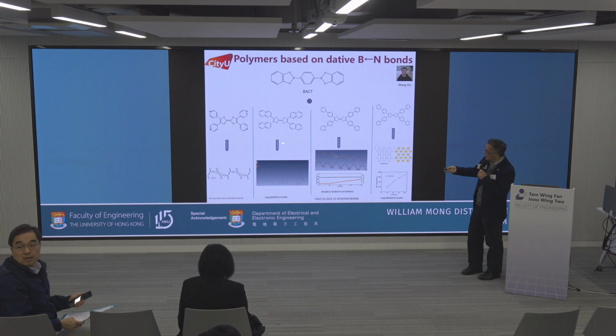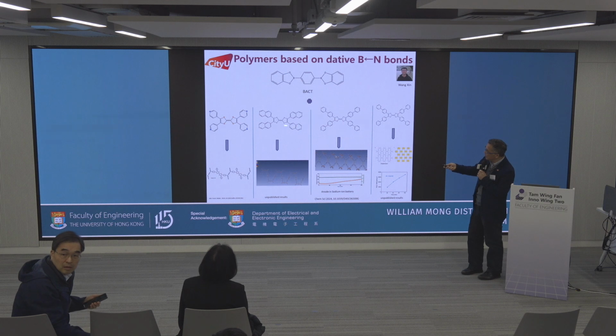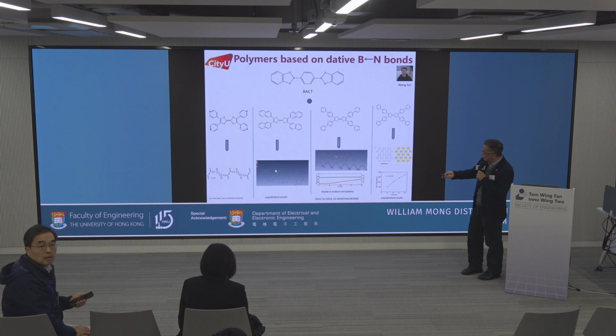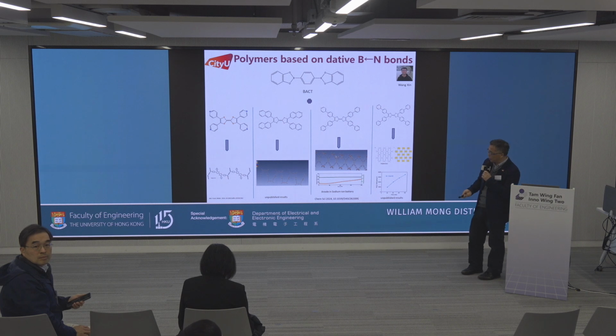isoquinoline, you can see that here it is still isoquinoline. The space is probably still not large enough, and in this system, they only use the 2 isoquinolines to do coordination. However, now you look at the BACT part. These 2 rings are in a cis configuration, compared to here, which is a trans configuration.